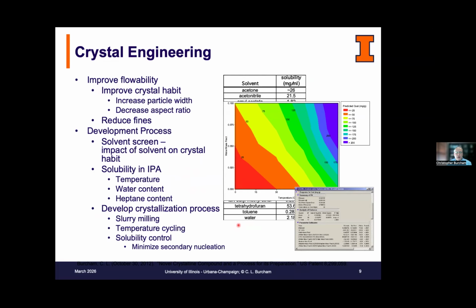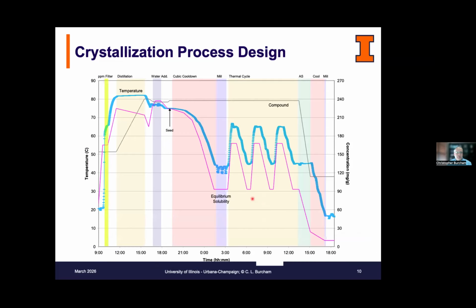We resulted then, through these efforts, in a process that's depicted here, where this was a recrystallization at the end of a reaction. It came out of the reaction. We had to concentrate it through distillation, and then we found through these experiments that the addition of water helped inhibit the growth rate in the axial direction and promote the growth rate in our radial direction. And so we're able to decrease the aspect ratio of our crystals by the presence of small amounts of water in our solvent system. We seeded the crystallization and then we cooled it down. This was essentially the same approach that we had taken in the material that was generated previously but didn't perform well.